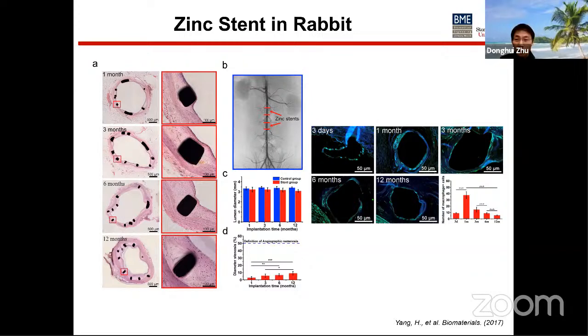We observed pretty rapid endothelialization on the material surface. The smooth muscle cell proliferation was low. The stent showed complete patency of the artery even after 12 months. The diameter vascular vessel stenosis is less than 10%.